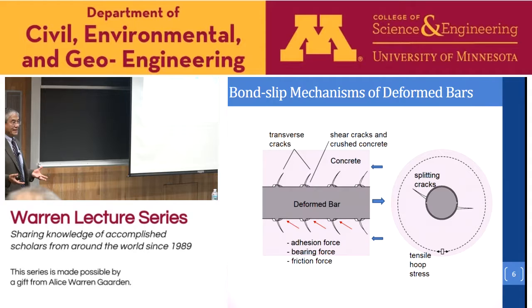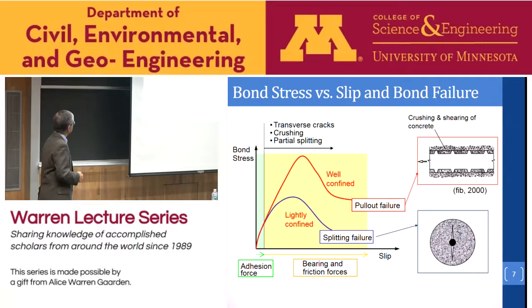So this just shows the bond stress, bond slip relation here. If we have lightly confined concrete, then normally the failure is the splitting crack like this. So it's very weak. If it's well confined, then it involves the crushing failure in the concrete. Sometimes the bar failure will be governed by the crushing of the concrete between the bar ribs, and then it will develop a sliding surface along here, okay?